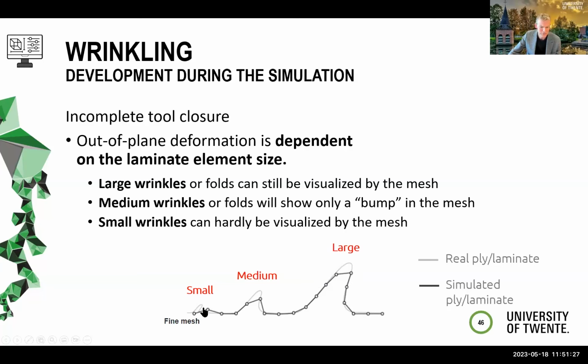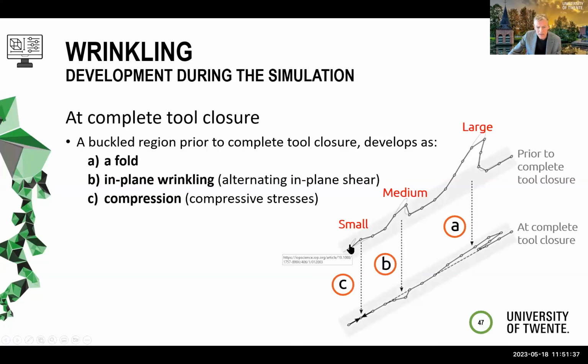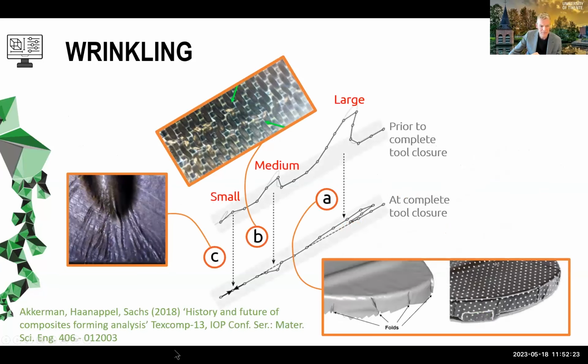But still, something may happen if there's a bit of compressive stress in the laminate direction. And then if we go from an open tool to a closed tool, the large defects will simply lead to folds at complete tool closure. The medium ones can be pressed between the two tool halves, and they can rotate to in-plane waviness. Whereas the small ones can be compressed, leading to compressive stresses without any in-plane waviness. So let's have a look at what that looks like. Here we've got these very small defects, some in-plane waviness, medium defects, and some large folds.